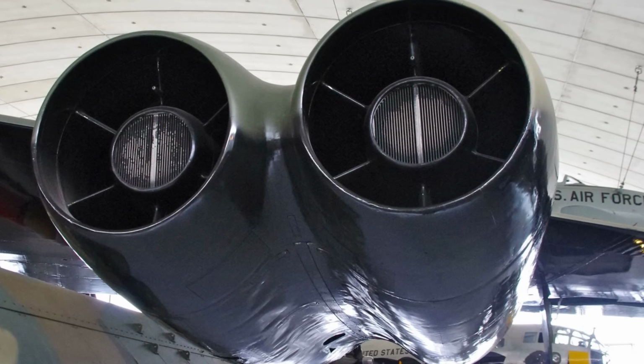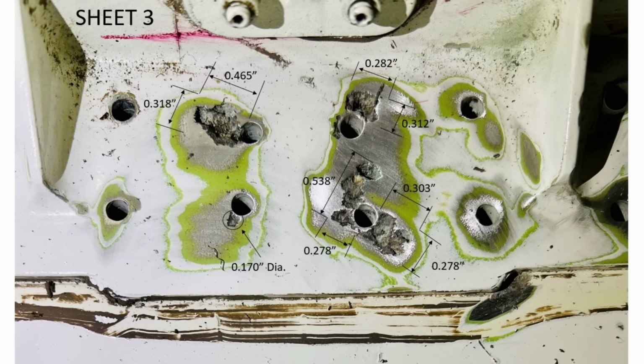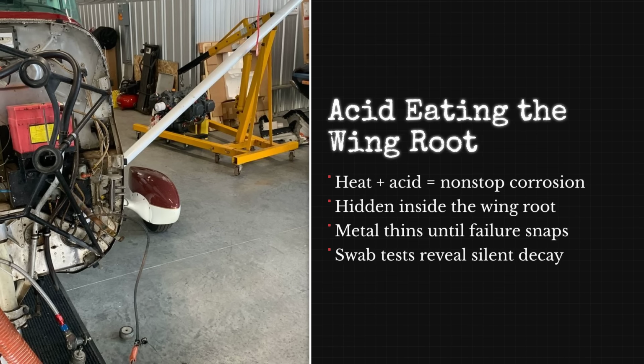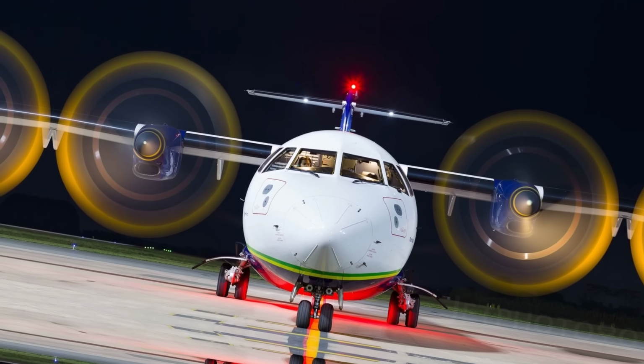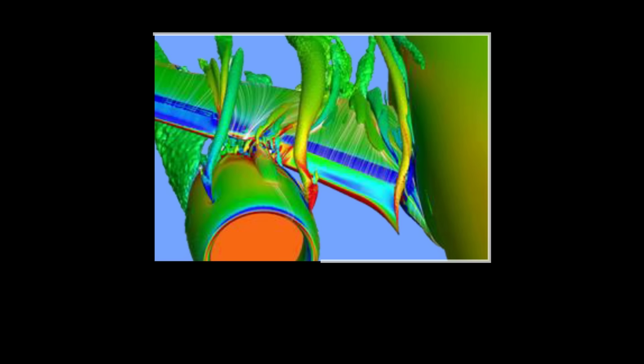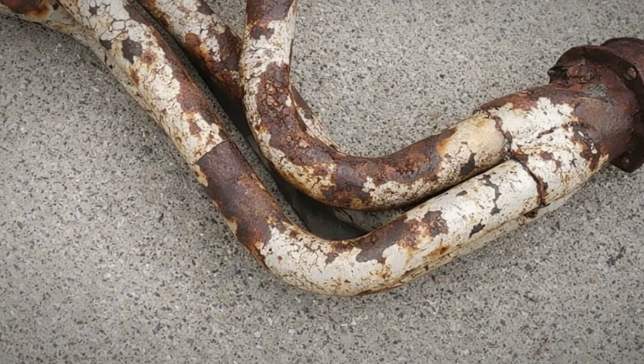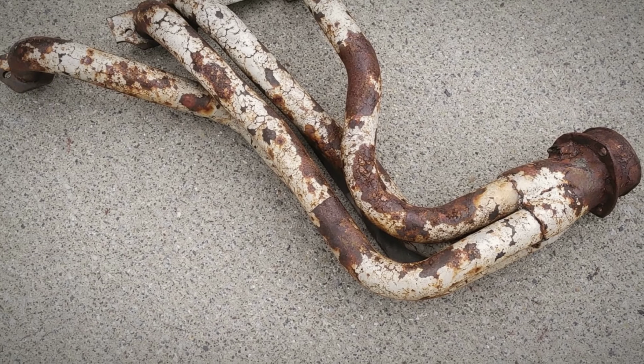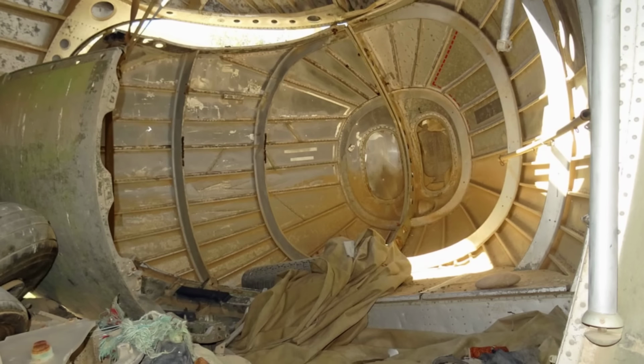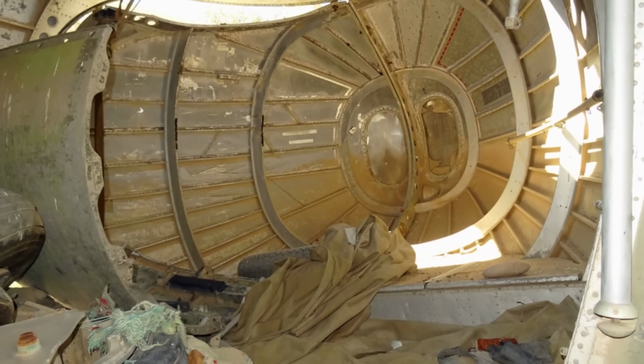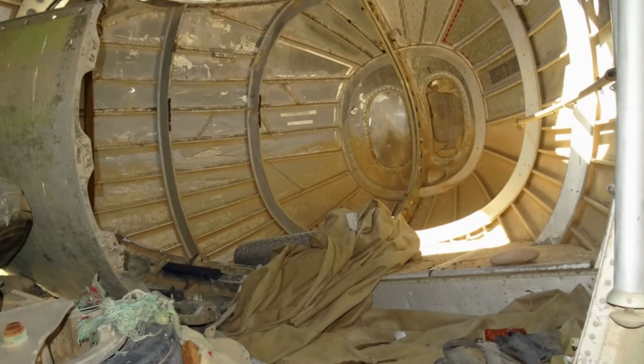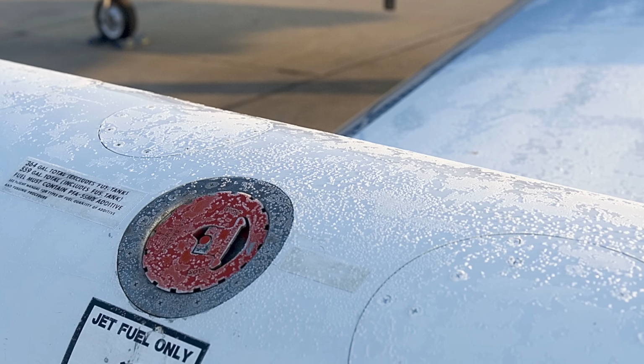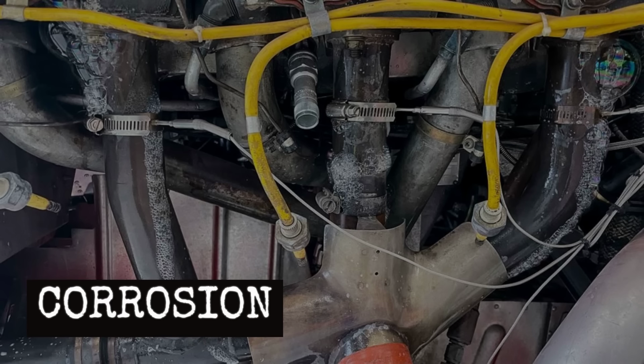But under the nacelle, where the wing meets the engine, there is a chemical war going on that most owners never see. The exhaust beam, a massive chunk of aluminum that holds the wing together, is under constant attack from 2 enemies, heat and acid. Every flight, the turbocharged engines pour out exhaust at hundreds of degrees, blasting the inside of the nacelle. That heat bakes the protective primer right off the beam, leaving bare aluminum exposed. Then the exhaust gases, full of acidic residue and chloride, settle onto the raw metal. Add moisture from a humid ramp or a leaky seal, and you have the perfect storm for corrosion.